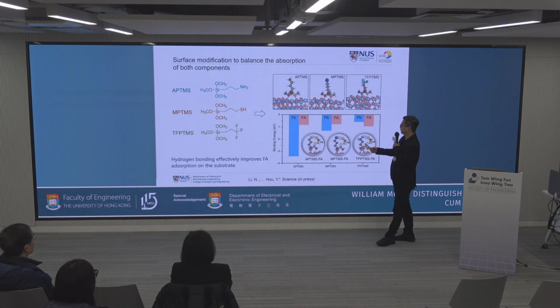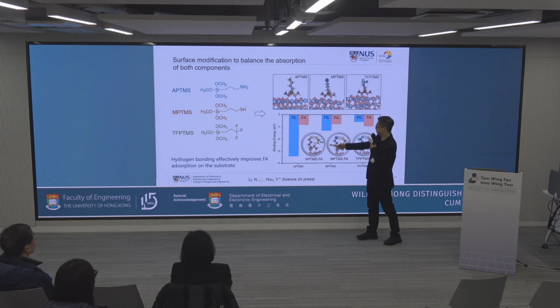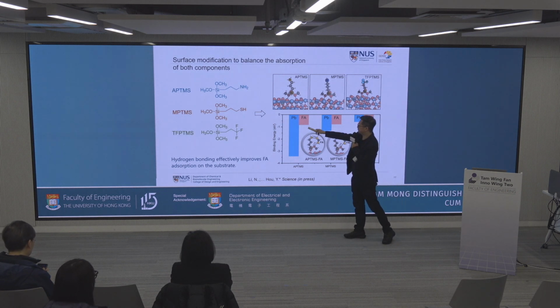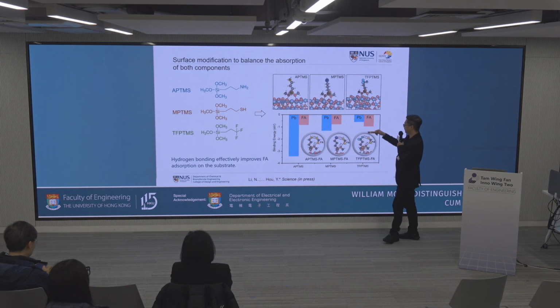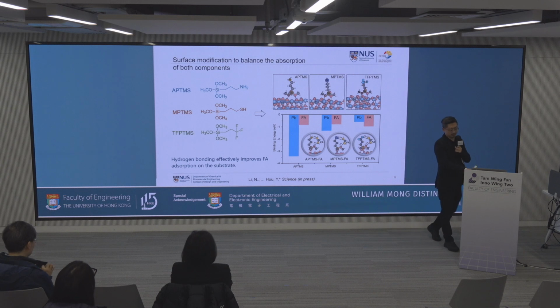Here is just our DFT simulation. We can see how we can use this structure to balance this. This is the inorganic lead component. This is organic, and before you see the very big gap in this binding energy, but in the end we can find this balance with these molecules.